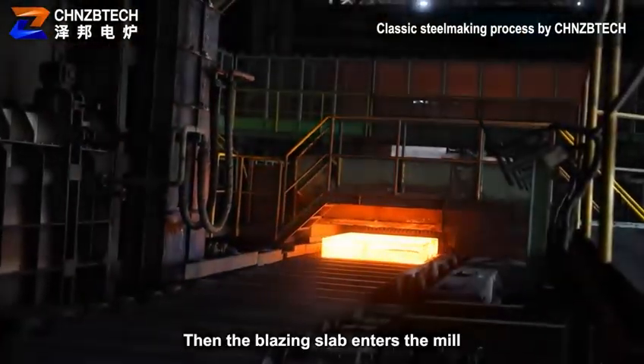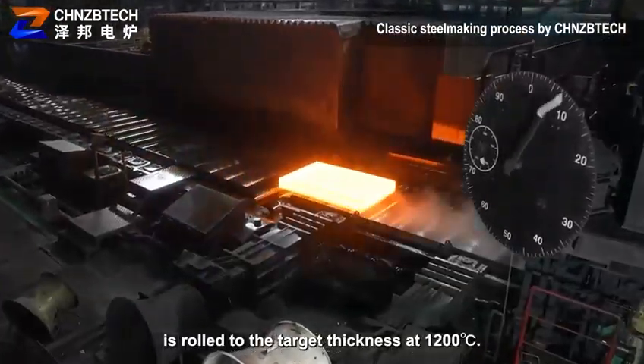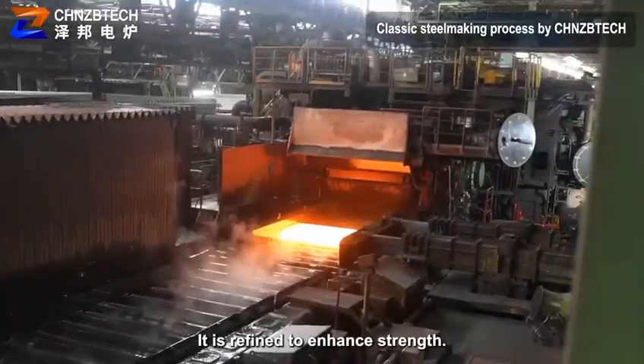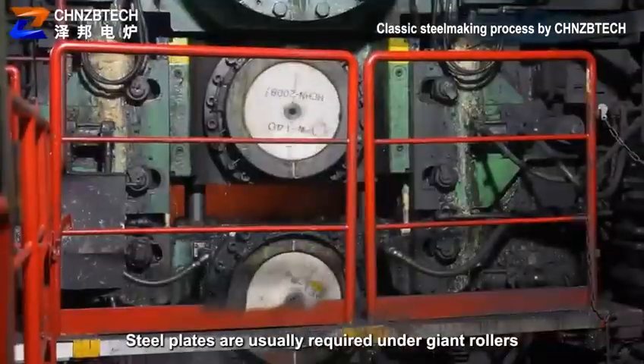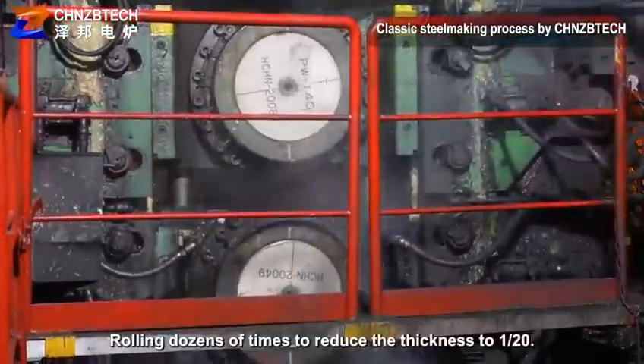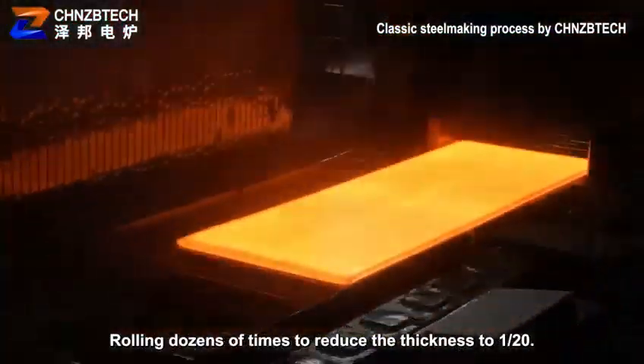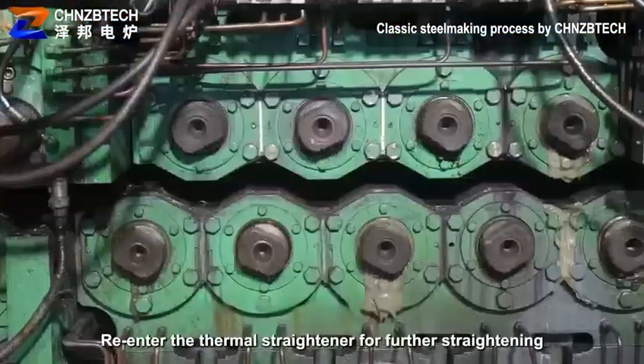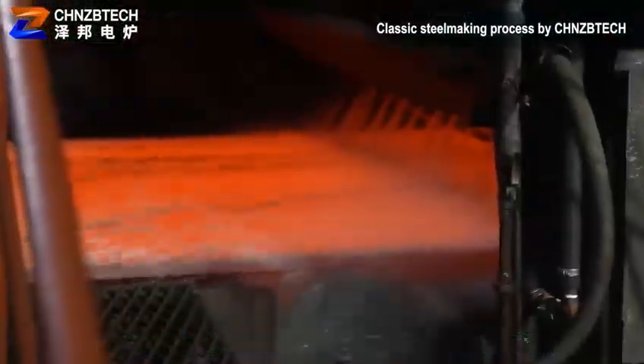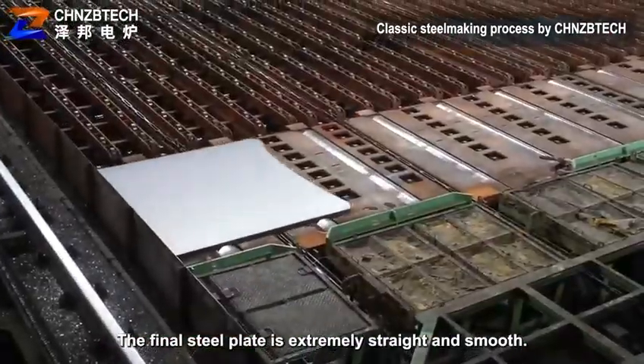Then the blazing slab enters the mill and is rolled to the target thickness at 1200 degrees. It is refined to enhance strength. Steel plates are usually rolled under giant rollers dozens of times to reduce the thickness to 1/20th. The steel plate with the required thickness re-enters the thermal straightener for further straightening. The final steel plate is extremely straight and smooth.